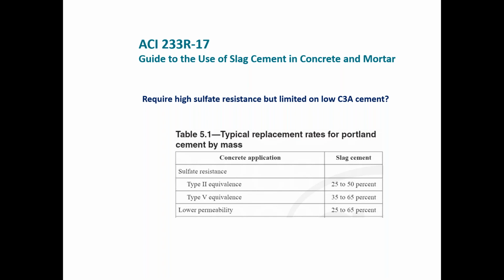So ACI 233, which I should reference, is the guide for use of slag cement in concrete and mortars, and here's their way to address the problem. If you want something equivalent to type 2 cement and you have a type 1 cement, use 25 to 50% slag. If you want something equivalent to type 5 cement and you're using type 1 cement, use 35 to 65. These are fairly good rules of thumb and very well supported.